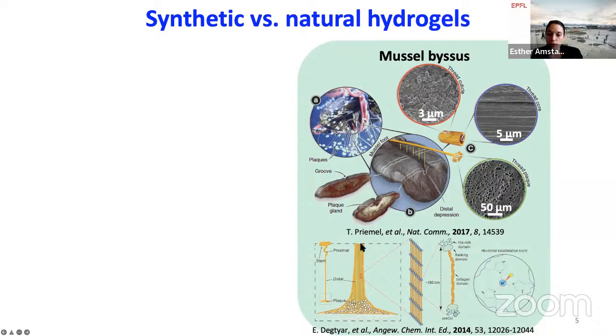But if you look at the mussel byssus, you basically see that it's made out of very different materials and structures. It's all protein-based, but here you have proteins that self-assemble into smectic liquid crystalline structures. There you have regions that are basically purely covalently cross-linked, and other regions that are purely ionically cross-linked. Then you have a shell that has a completely different composition and structure, and yet you have a plaque, the adhesive part, that has yet another composition and structure, as you see also in these scanning electron micrographs here. And I think really the combination of this very precisely controlled local composition as well as structure on different length scales in the end allows nature to build these kinds of high performance soft materials.